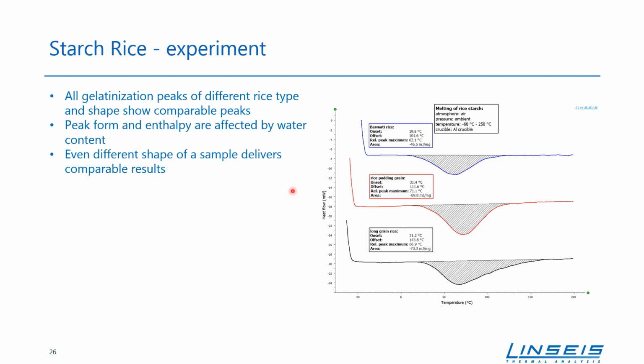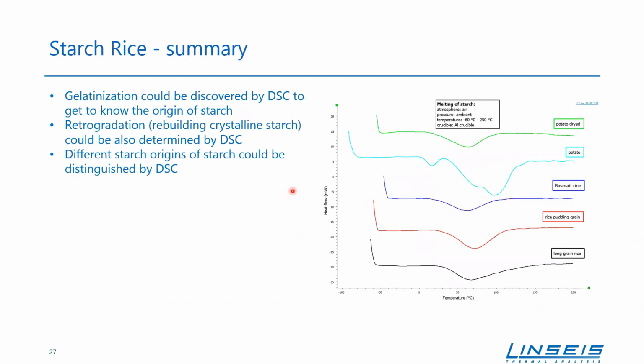But the shape is really different for our different samples. And this is caused by the humidity. These peaks are really affected by the water content. But they are comparable. So we've added, for example, potato. Now in cyan and in green, you can see potato. One of the samples is dried and the other one is a fresh potato. Here we can see a huge difference between these 2 samples in comparison to our rice starch. So even if you don't know the origin of your sample, it's possible to separate them by DSC and distinguish them.